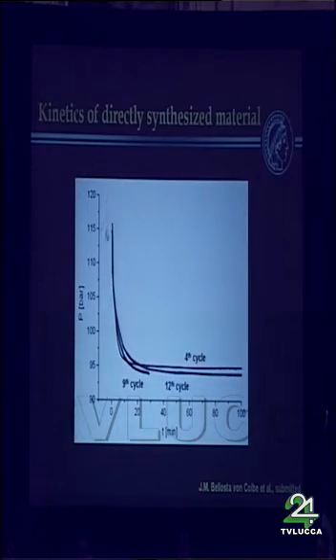The big advantage of this method is the extremely fast kinetics. The kinetics of this directly synthesized material, milled under hydrogen pressure, is about as fast as for the materials which I would consider the best ones known before, which are the colloid materials, which Maximilian Fichtner had described 2 years ago, where you use titanium colloids. The direct doping under hydrogen pressure with titanium trichloride gives you roughly the same kinetics. It's all over in, I would say, less than 15 minutes, and the cycle stability is rather high for these materials.